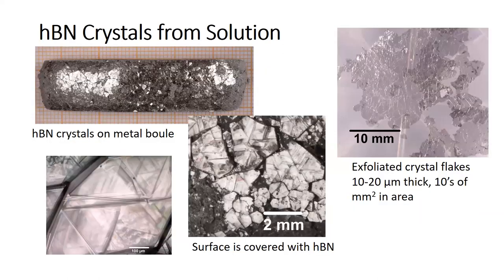So this is typically what comes out of our process. We have our solidified boule, and then the boron nitride precipitates on the surface of the melt as it freezes. As individual crystals, there are a couple of different morphologies. Either we can have individual crystals that are separated like this, or we can have sort of a continuous film like this. Depending on the conditions we grow, we can then peel those off to have pretty big freestanding flakes. Typically these are tens of square millimeters in area and 10 to 20 microns thick.